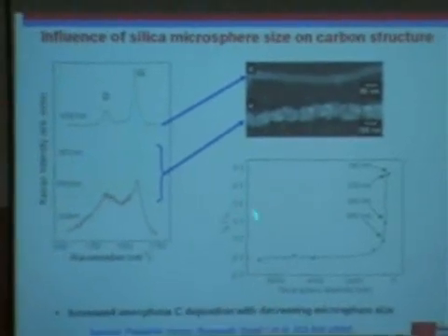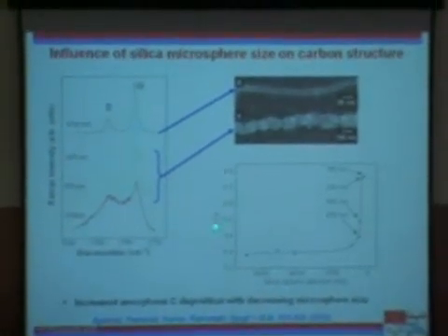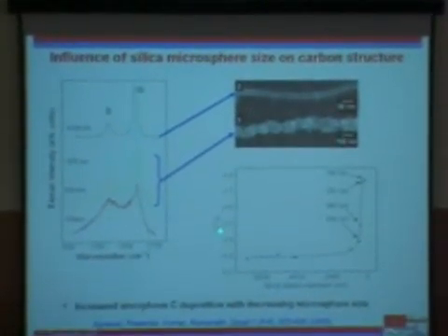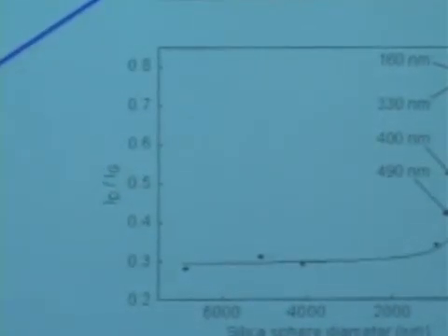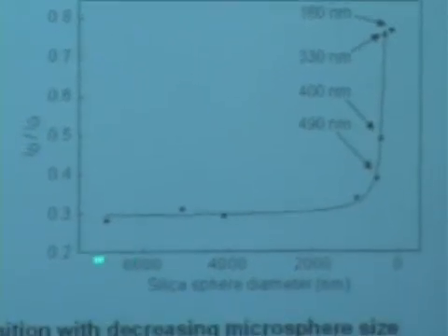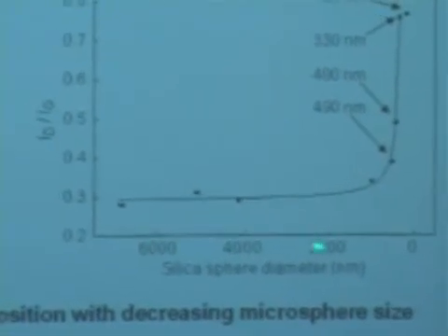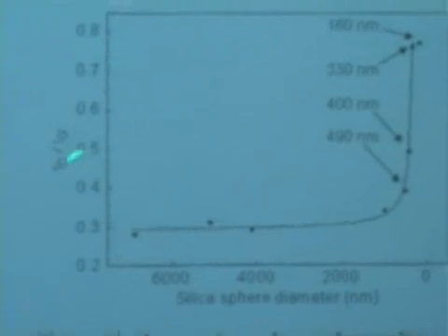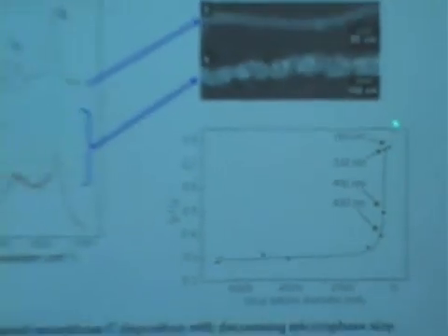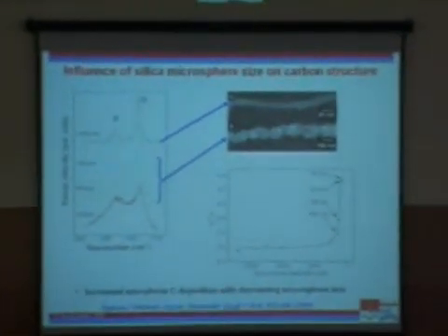But that is actually captured in this particular picture nicely. This is the Raman intensity of the D and G band. D represents disordered carbon, G represents graphitic carbon, which comprises carbon nanotubes. And as you decrease silica sphere diameter, you can see that the disordered part really shoots up, okay, and you don't get carbon nanotubes anymore.